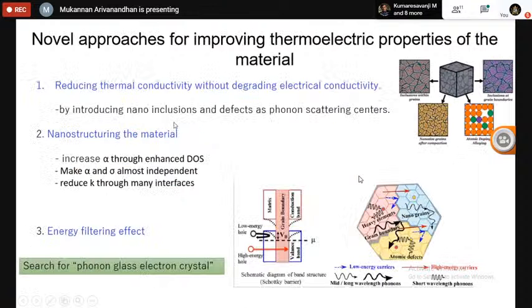And these are all the novel approaches that people are following to improve the performance of thermoelectric material. Okay, so the first aspect is reducing the thermal conductivity without affecting the electrical conductivity. That is the first idea. For that, you have to introduce some kind of nano inclusions or defects as phonon scattering centers, and that will help control the thermal conductivity without affecting the electrical conductivity. Okay, and nanostructuring the material. This is another important approach.